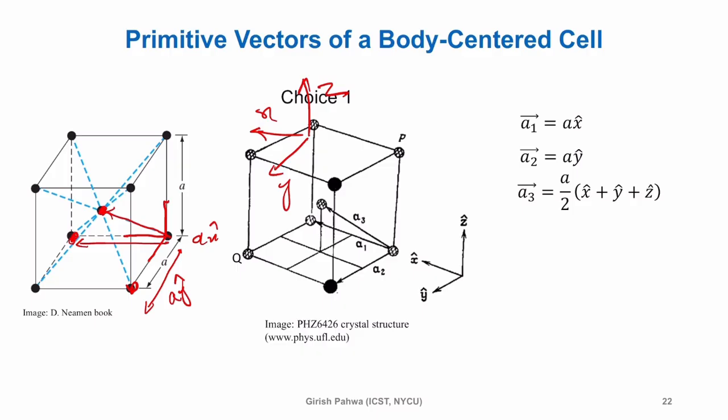But the volume created by the 3 vectors, it will be a parallelepiped. So there is a parallelogram, and the 3D version of that is a parallelepiped, right? So the volume of the parallelepiped is this: A1 dot A2 cross A3. A1 dot product of A2 cross A3.